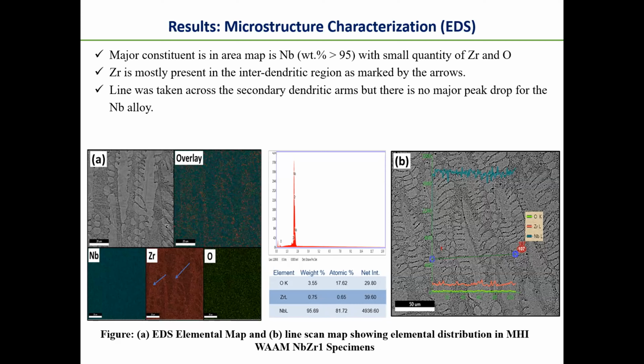Then we did some EDS to find the elemental distribution. We did first the area mapping, and then the line scanning. In the area mapping, we found that the major constituent was niobium, which is more than 95%, with very small trace quantities of zirconium and oxygen. In the zirconium map, we found that zirconium is mostly present in the interdendritic region. On the contrary, niobium and oxygen are both homogeneously distributed across the microstructure. Then we performed the line scan to find if there is any elemental change in the dendritic or interdendritic region, but the line scan showed no major fluctuation in the peak of the pure niobium.